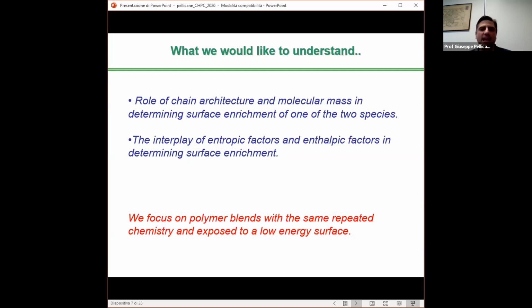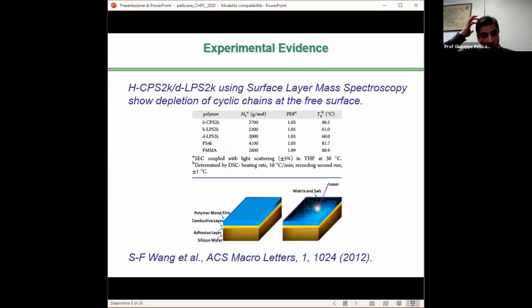So considering polymers with the same chemistry and different architecture, such as linear and cyclic polymers, allows one to better understand the role of conformational entropy, and as we shall see later, also other forms of entropy. The focus of the results I'm going to present is on low energy surfaces, such as vacuum or air, where the polymer species with the lowest cohesive energy density, or if you want, with the lower solubility, is generally favored, since the potential energy cost of separating the melt and producing a surface becomes minimized.